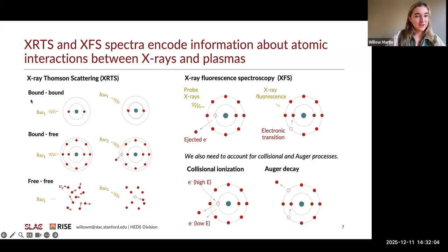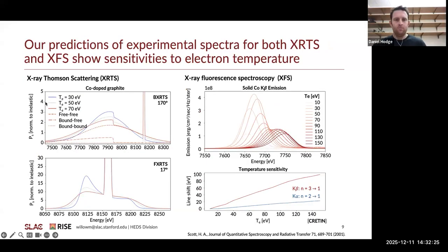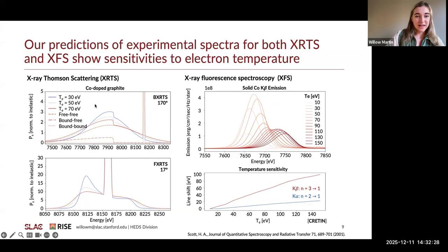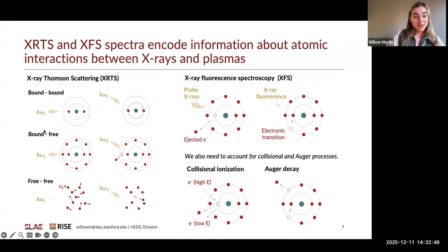Then another class of interactions you have to consider are bound-free interactions, where radiation comes in and effectively ionizes electrons that were originally bound to an ion. Just like the edge features you're probably familiar with from calculating filtration, you similarly get an edge feature here, where there's a gap between your elastic feature and your bound-free edge. The contribution to the scattering signal in this regime is coming from electrons that were sufficiently energetic to ionize K-shell electrons from the carbon. Lastly, we have the free-free interactions where the radiation interacts with the ionized electrons.